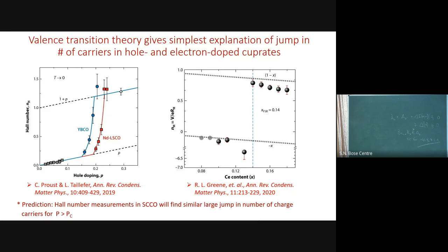But the thing that people have forgotten, which they were interested in way back, is that in yttrium barium copper oxide, you saw plateaus in TC. Nobody talks about that. If you look at the Hall coefficient, you see a jump by a factor of 2. If you go through this and look at all the other parameters, you will see that the lower plateau, I can explain with one of the layers becoming copper 1+. The higher one is the next one. I can go through it stepwise. It cannot be done here.